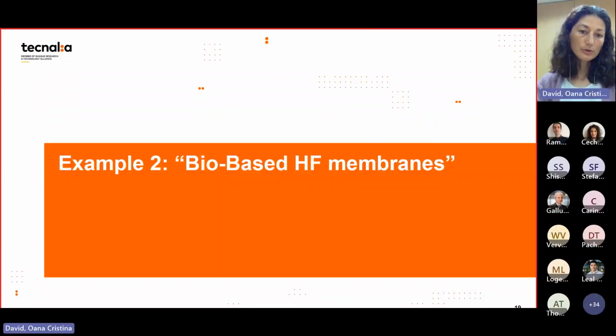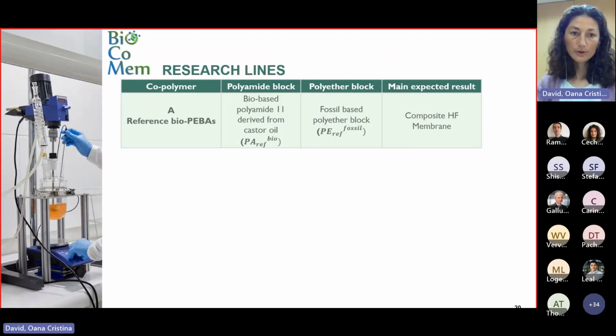So now I will go to example 2, bio-based hollow fiber membranes, the ones we are doing in the Biocomem project. And here, just to have an overview, we have 3 research lines. The bio-PEBA line is a polymer that was already developed by Arkema at the beginning of the project at TRL 7, and they even increased the production, so they have it for some other application. But it's very good for carbon dioxide separation, and it's half bio-based because only the polyamide block is bio-based. It comes from polyamide 11, which is derived from castor oil. The polyether block is fossil-based, and then Herion will show you the results of composite flat sheet membranes.